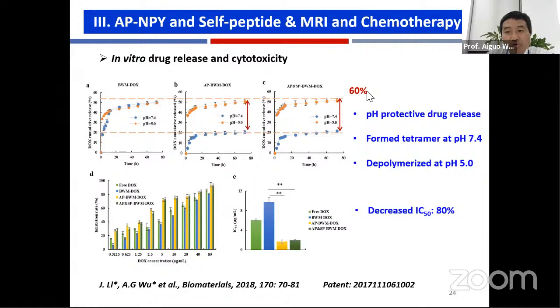drug release system, and it forms a tetramer at the normal pH of 7.4, and at a lower pH, for example pH 5, it dissociates. And we found this system can decrease the IC50 by about 80%.